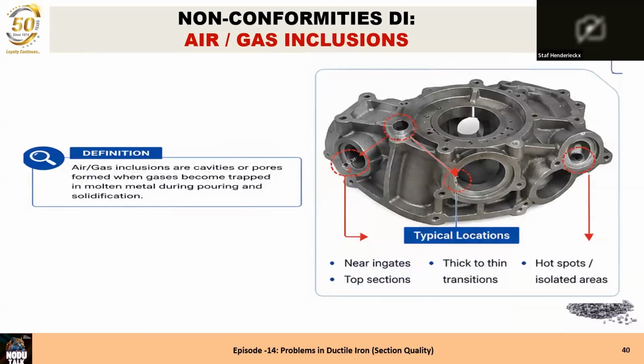Always you will have a smooth wall on the defect, because it's gas and air, and gas and air doesn't make a rough wall of the defect itself. Where can it be? It can be near the ingates, mostly at the top sections. It can be where there are thick to thin transitions, and it can be at the hot spots. But let's say in 60 to 70% of cases, it will be on the top of the casting.